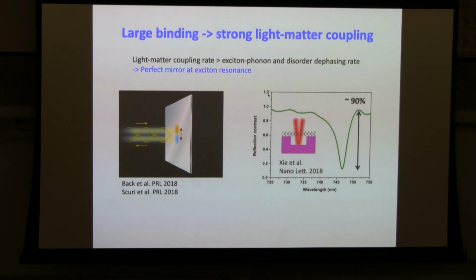So at the exciton resonance, the material, even though it's just a single layer of material, actually acts like a perfect mirror that reflects almost all the light that you shoot into the sample. This is an example here which shows the reflection contrast of a monolayer of tungsten selenide, a suspended structure. You can see that even though it's a monolayer of material, at the exciton resonance it can reflect about 90% of the light because of the very strong excitonic binding in the system. You can estimate the line width from this measurement to be about 5 milli-electron volts, and that is really the light-matter coupling rate, and that limits the exciton lifetime to about a picosecond. So the very strong binding at the same time means that the excitons are extremely short-lived, and you don't have enough time to equilibrate them to reach the condensed state.